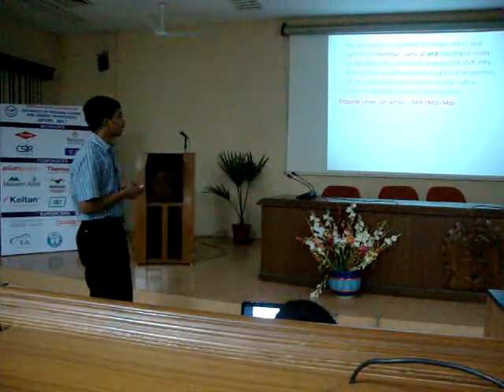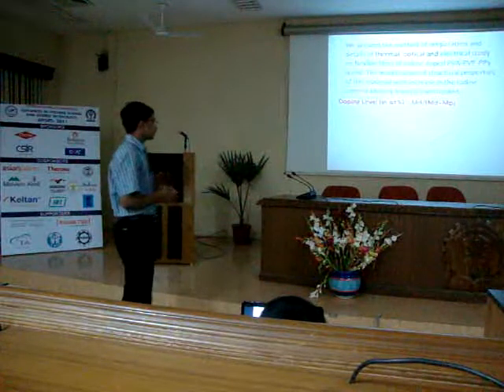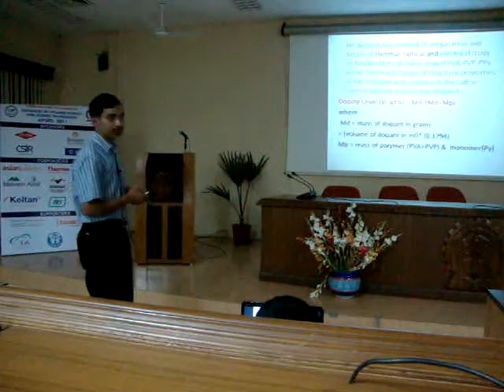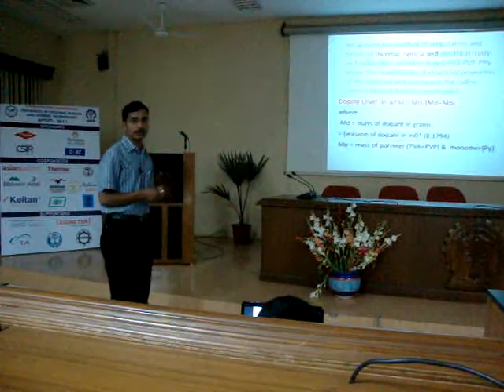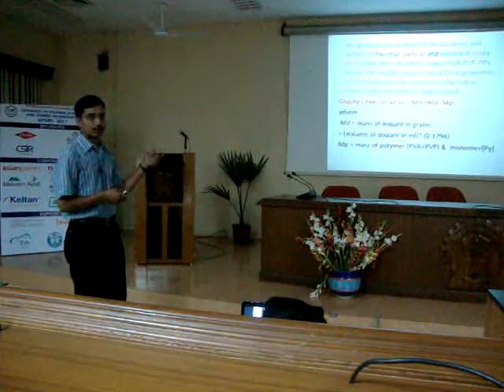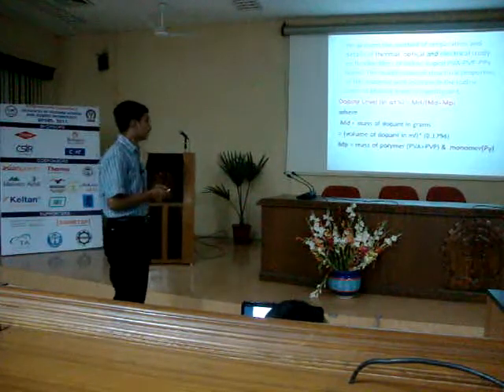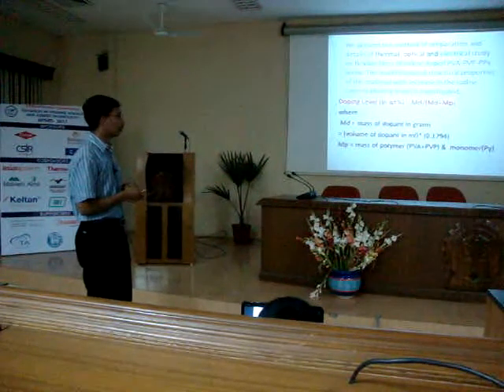Doping level in weight percent is equal to MD divided by MD plus MP, where MD is the mass of the dopant in grams, which is equal to the volume of dopant in ml times 0.1794. So 0.1794 is obtained as I will explain in the next slide. MP is the mass of the polymer, that is PVA and PVP, and the monomer PY.